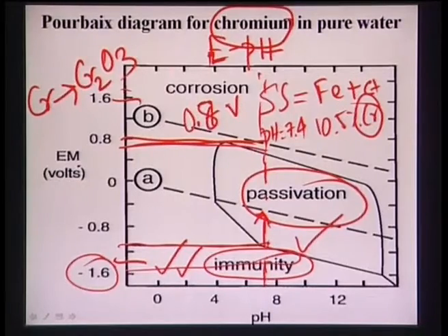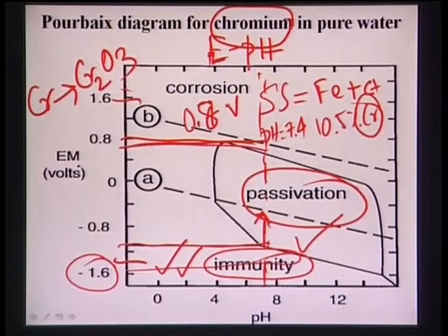So, at higher electrochemical potential range, although there is sufficient amount of chromium which otherwise gives you good corrosion resistance, that will not serve its purpose. Okay. So, the message that I am trying to give from this slide is that inside the in vivo conditions, or inside the human body, even if you put the stainless steel, it will not protect you from corrosion if the electrochemical potential value is 1 volt or more than 1 volt. Okay. So, then the stainless steel itself will undergo corrosion.